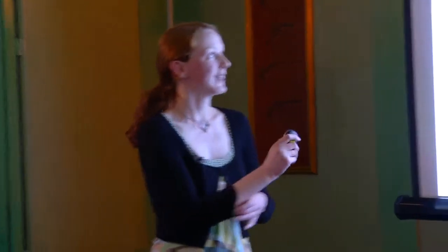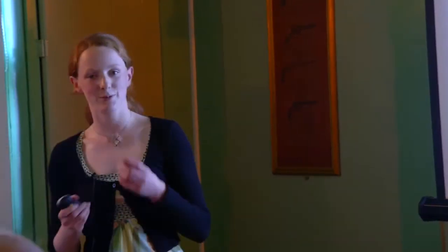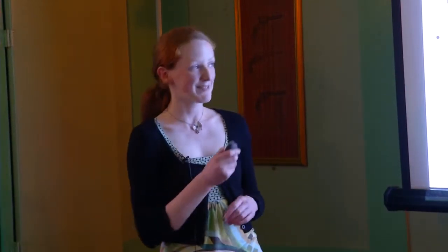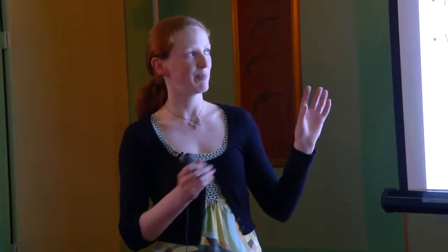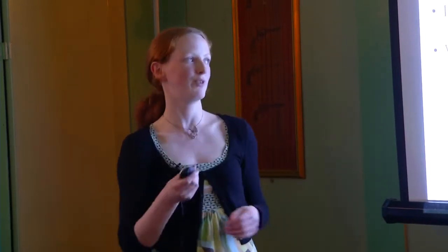So how does that work? How do you combine the two? Well, there are two different ways. You can have single phase. This is where you take one material that both has the ferromagnetic memory and the ferroelectric memory. But there are problems in that they're very rare in nature, and those that do exist only work at extremely low temperatures. So you'd have to put your iPod into a vat of liquid nitrogen or liquid helium, which isn't very practical. So instead, you can take the ferromagnetic memory part, the ferroelectric memory part, like here, and just stack them on top of one another.